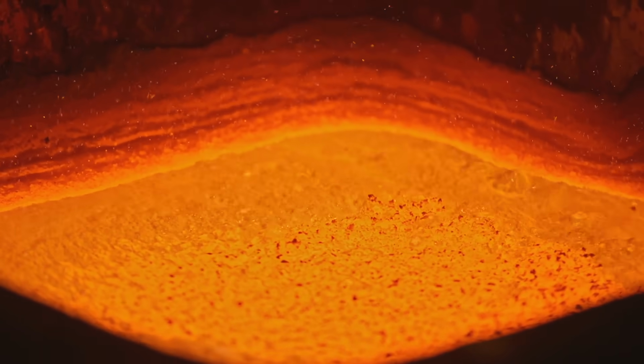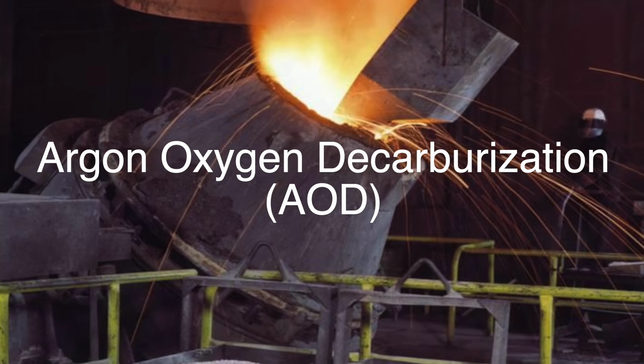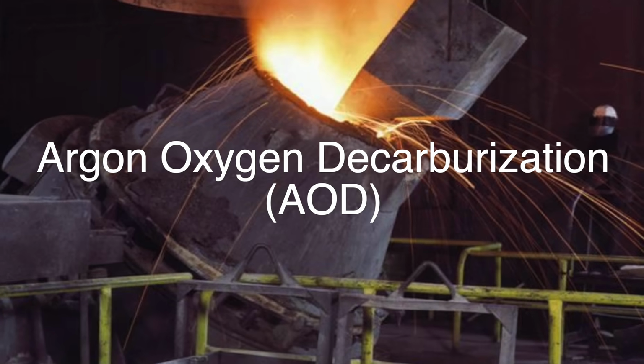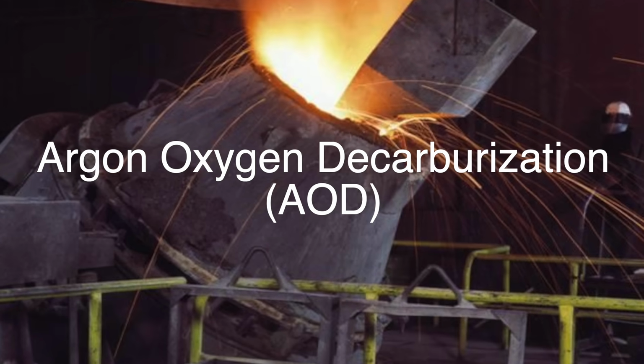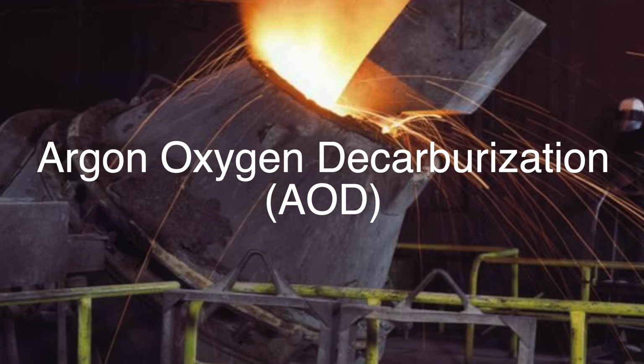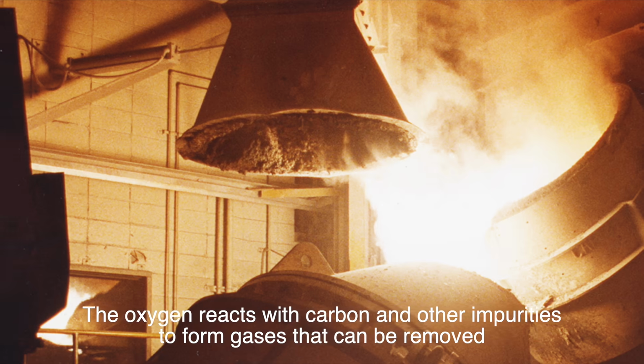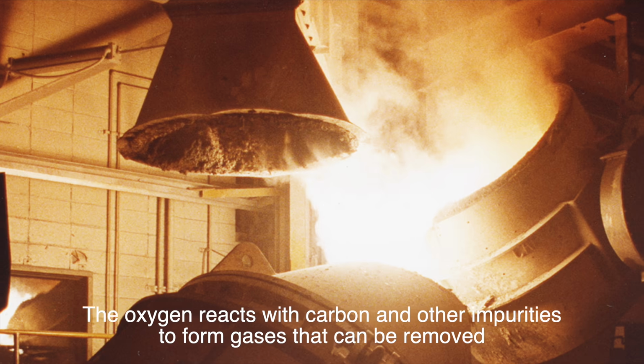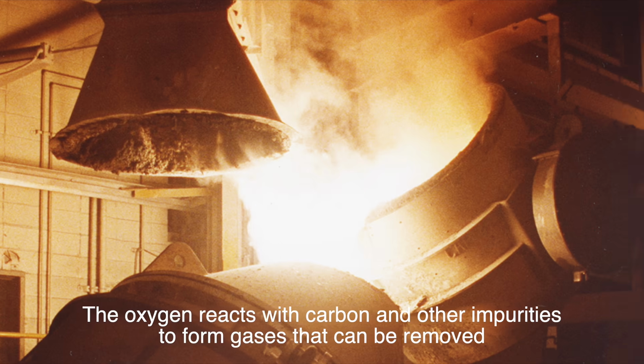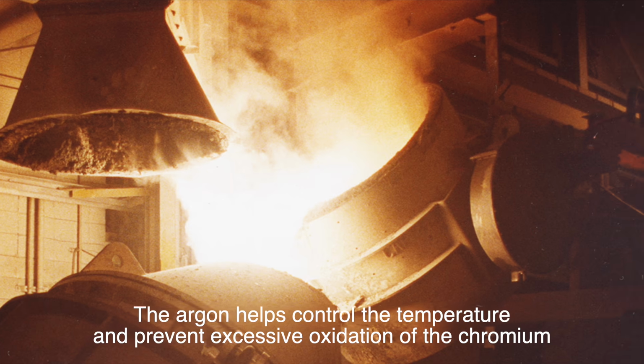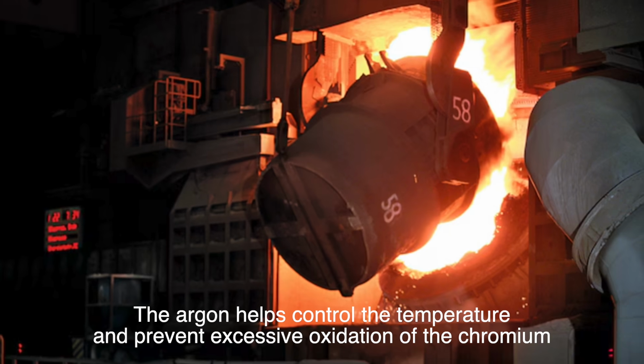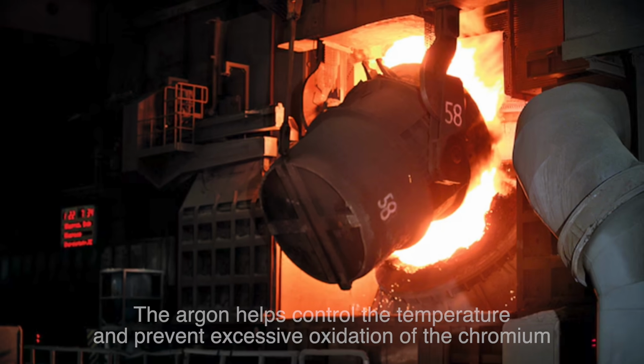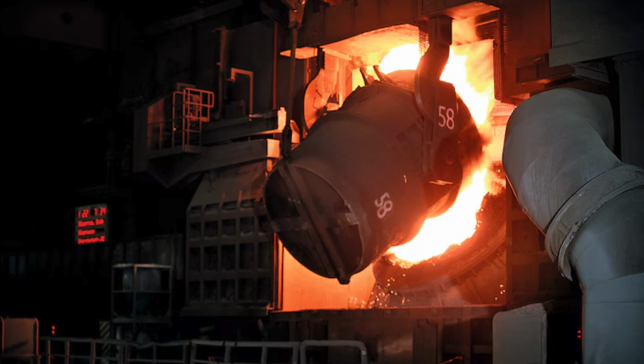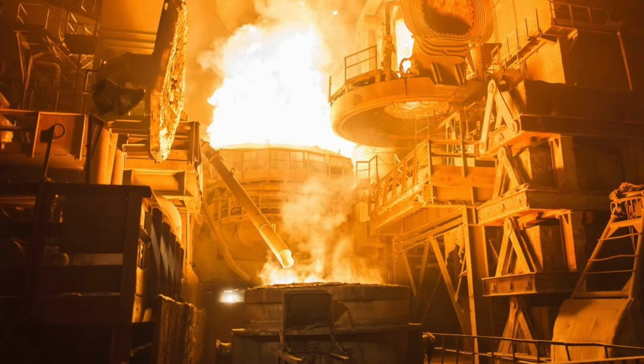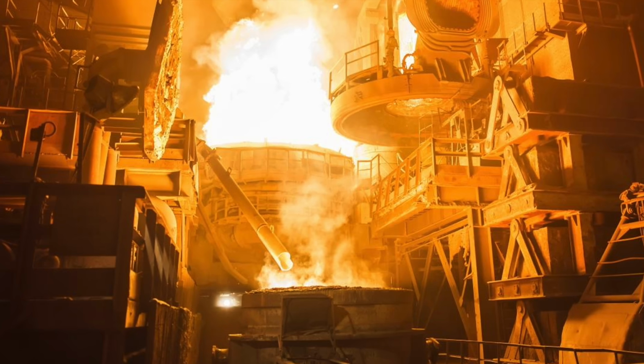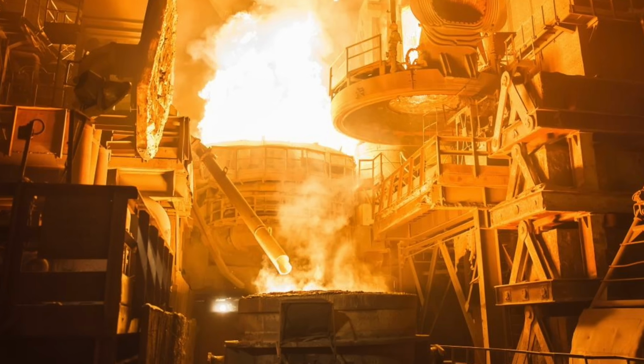This is done through a process known as Argon Oxygen Decarburization, AOD. In AOD, a mixture of argon and oxygen is injected into the molten steel. The oxygen reacts with carbon and other impurities to form gases that can be removed, while the argon helps control the temperature and prevent excessive oxidation of the chromium. The result is a purer form of stainless steel, with a carefully controlled composition that ensures the desired properties are achieved.